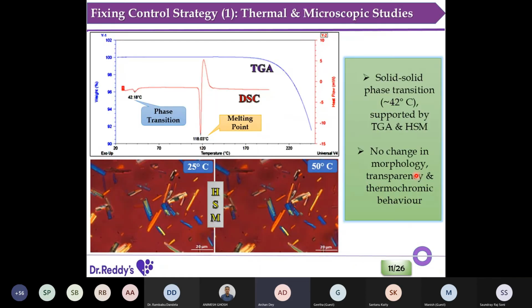So we took a very simple experiment. We did DSC and TGA. What you can see is a phase transition around 40 degrees Celsius, just way before melting. And as per TGA, it's very clear that there is no residual water or residual solvent loss. So that indicates it's a solid state to solid state phase transition. And a more surprising thing came when we did hot stage microscopy. We heated the material gradually, but I am showing the endpoint only. What we saw is that there is no change of any crystal morphology, even in the birefringent patterns. It's a big surprise.